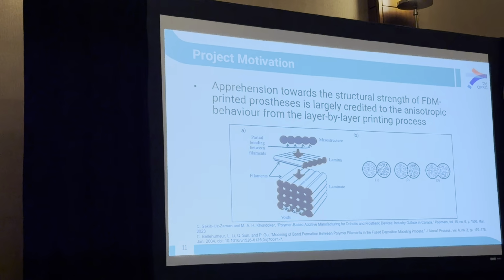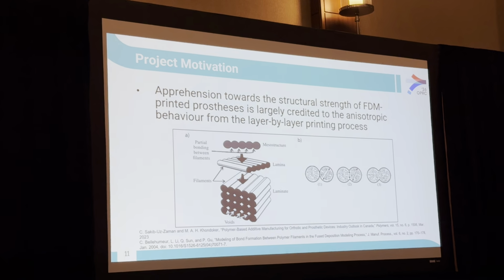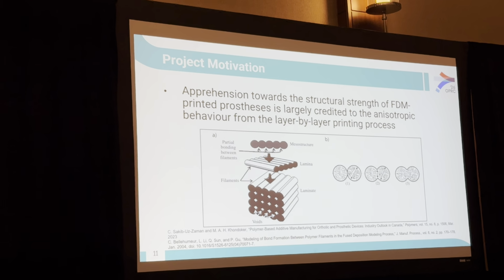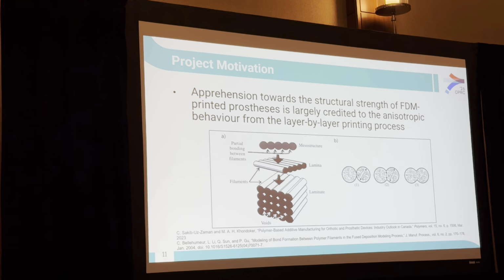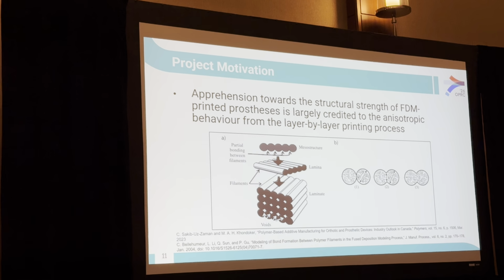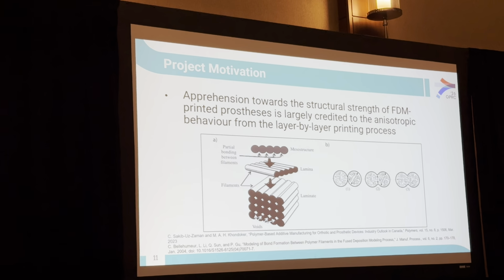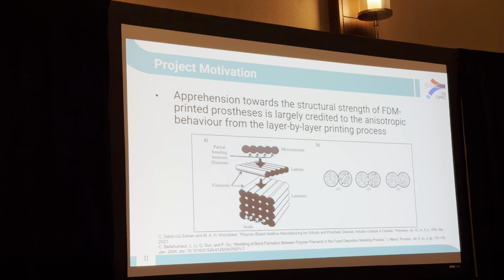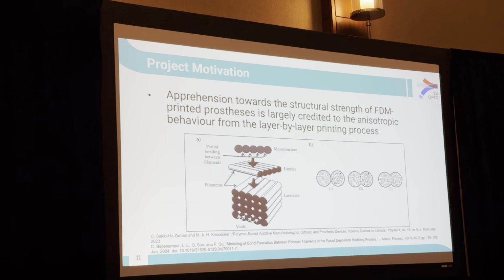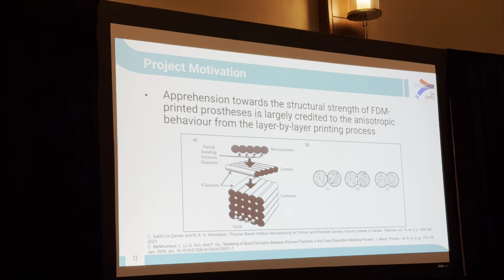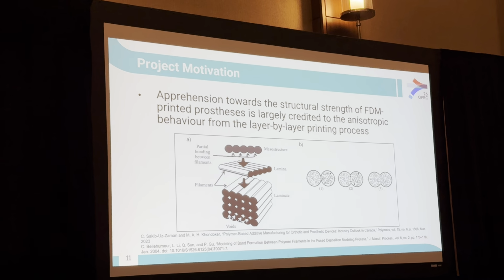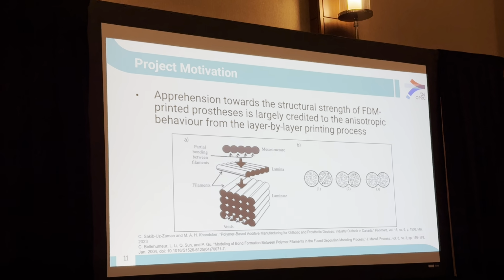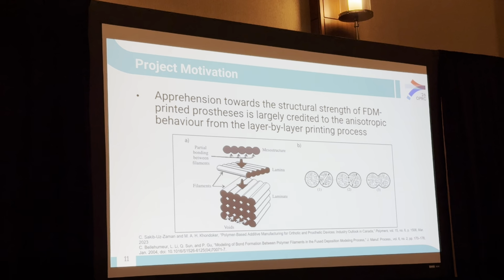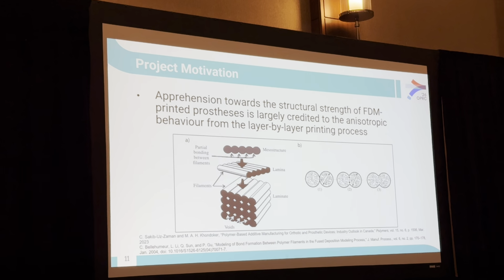The reason for this apprehension relies on that layer by layer manufacturing method. This is because this method creates what's called anisotropic material behavior, which means the parts produced with these manufacturing methods show directionally dependent behavior. If we look closely at what's going on, as these layers are deposited, there's a partial bond between the filaments, but there are also these little voids that lead to this directionally dependent behavior.